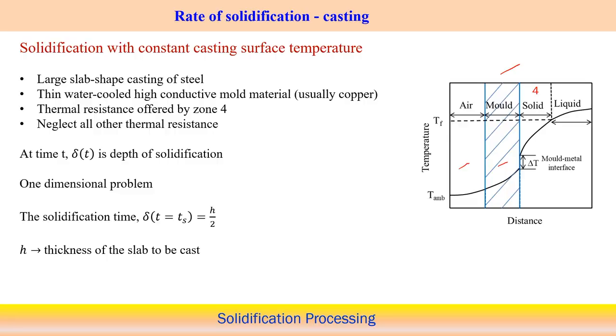So, in this particular situation, with very large slab casting and a very thin copper mold material as well as water cooling, the thermal resistance is actually offered by zone 4. Zone 4 is where some solidified metal surface has been created in contact with the mold surface, and whatever thermal resistance is there is because of the already solidified component in this casting process. So, in this case we can neglect all the other four thermal resistance components, and based on that we can analyze the rate of solidification, or the solidification time in this particular situation.